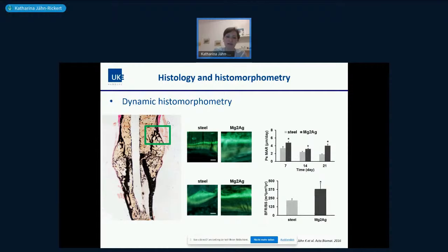So we did this here in this fracture model that I've mentioned before, and we wanted to look at the bone formation within the fracture callus, or the formation of the fracture callus. We had our groups again of a steel implant and magnesium implant, where we looked at the cortical bone here, the fracture callus, but also the trabecular bone, which is seen in the lower part. And one can look for the mineral apposition rate, so really how many micrometers of bone are made per day. And this can also be translated into what we call the bone formation rate.